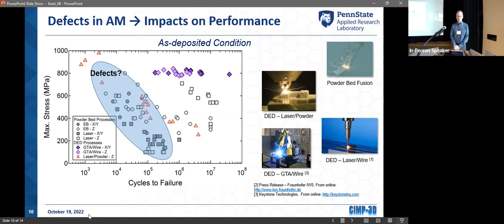I would say 80% of the fatigue that you see is in titanium and nickel-based alloys. But what I've seen is I think we are comparable to conventional wrought-based products, but there are still issues on steels, and I wouldn't be able to answer that at this time. Is there a real fatigue limit that we don't have to worry about it ever breaking?